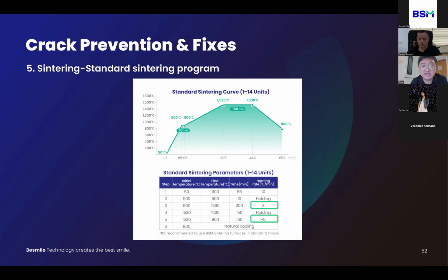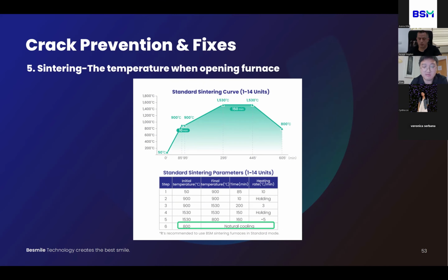Another thing that we need to pay attention to is the temperature when opening the furnace. You can see the program finishes at 800 degrees. After that, it's natural cooling. If we open the furnace at a high temperature, the restoration will suddenly be exposed to cold air and crack easily. So we recommend the opening temperature should be lower than 500 degrees for the single unit and small bridges. And for the long bridges and the full arch, the opening temperature of the furnace should be lower than 300 degrees.